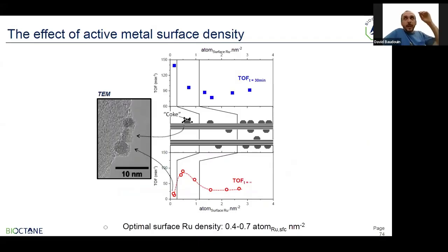Now it turned out that we have observed some signs that the loading had some effect on the performance of the catalyst, and we are further investigating that. And actually, by plotting the turnover frequency with regard to the surface loading of ruthenium, we find the same correlation for the initial turnover frequency, but we also find some correlation that actually makes sense with the stabilized turnover frequency. And it seems that there is an optimal surface loading of ruthenium that was found for CNF, but also for activated carbon. Next slide, please.